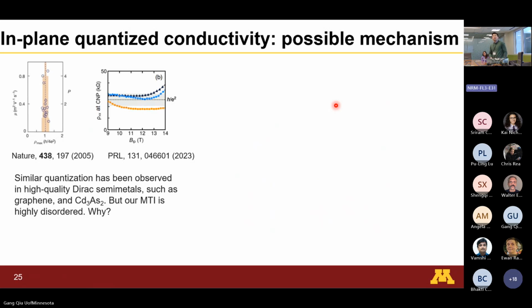If you look at the literature, there are not many examples of in-plane quantization. We know there's quantum Hall and quantum anomalous Hall, and these states always happen in the Hall direction. The only time you see a longitudinal resistance quantization is in, let's say, quantum point contacts, like nanowires, or even in some quantum spin Hall states, where you have limited modes of electron states in a restricted region. All these quantized longitudinal resistances happen in the resistance, meaning it's independent of the aspect ratio. But in our case, it actually happens in the conductivity, or you have to normalize it with your geometry. So this is a very special case.